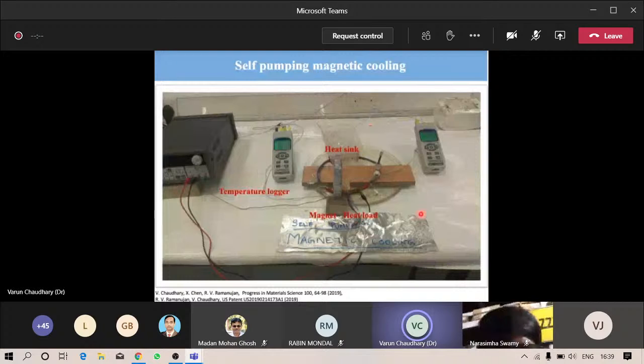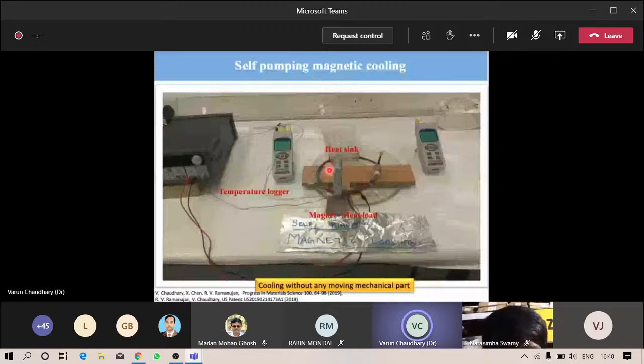So this is the very first picture of what we developed, the self-pumping magnetic cooling. Here you see a circular tube filled with ferrofluid, and here we have a heat load, and this is a permanent magnet which can apply a field of 0.3 Tesla, and this is the heat sink and some temperature loggers to measure the temperature. So when we apply the magnetic field, the ferrofluid starts to circulate, and the heat from this heat source is transferred to the heat sink. So cooling without any moving mechanical part.